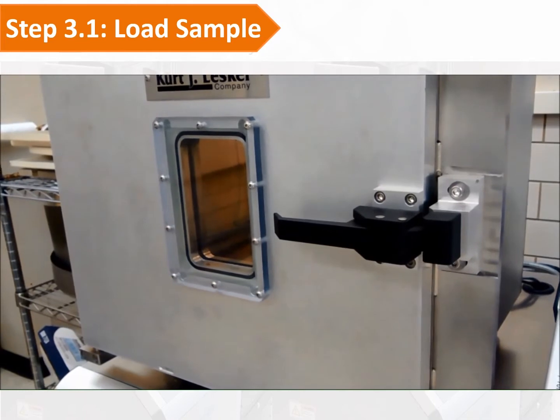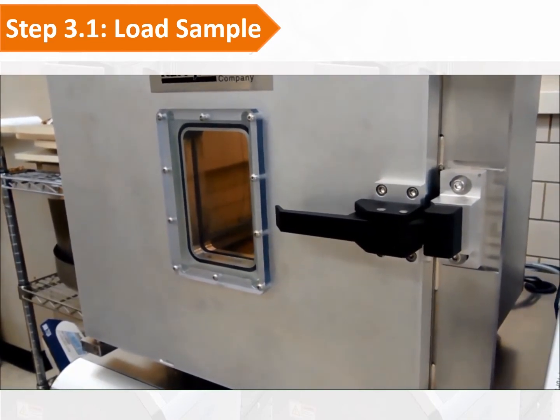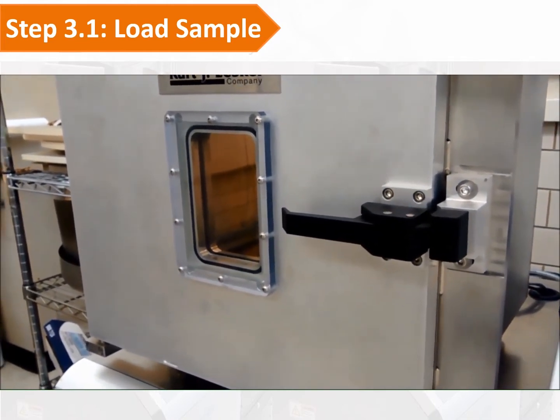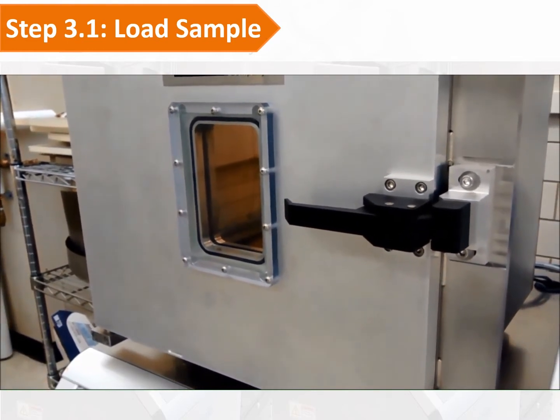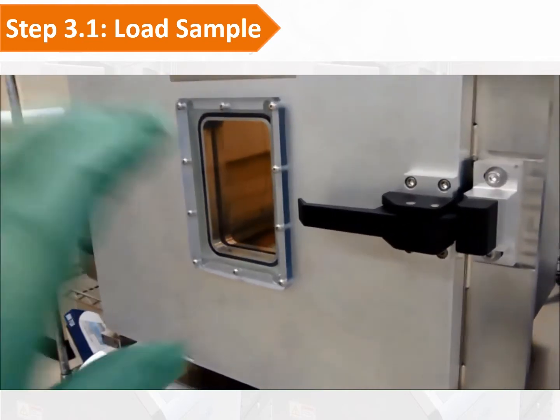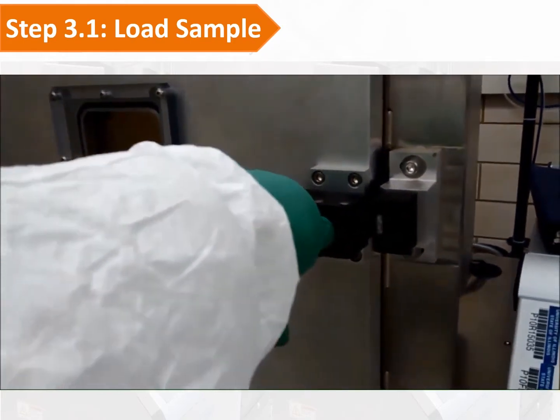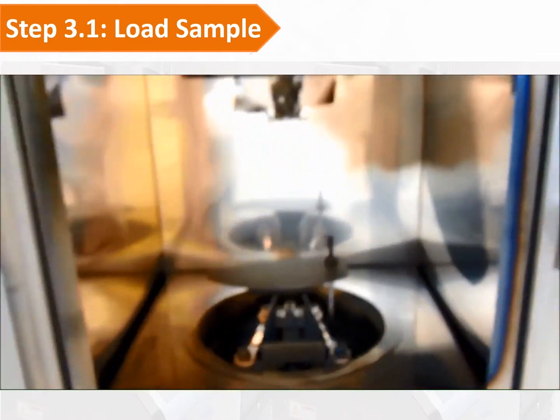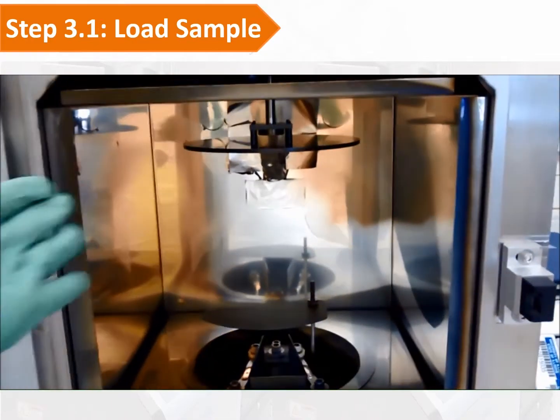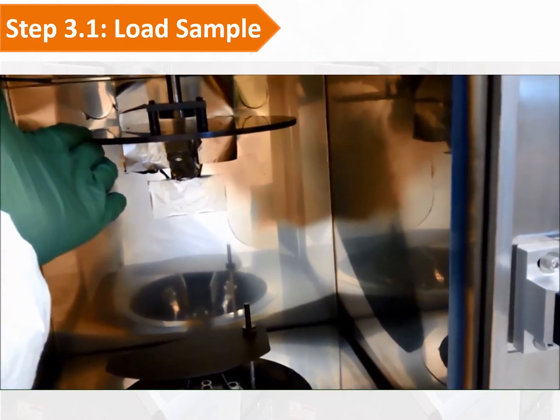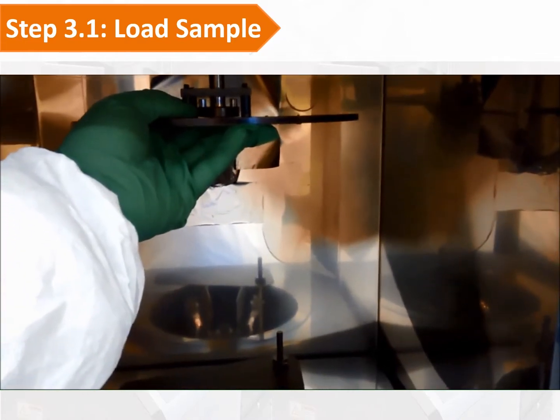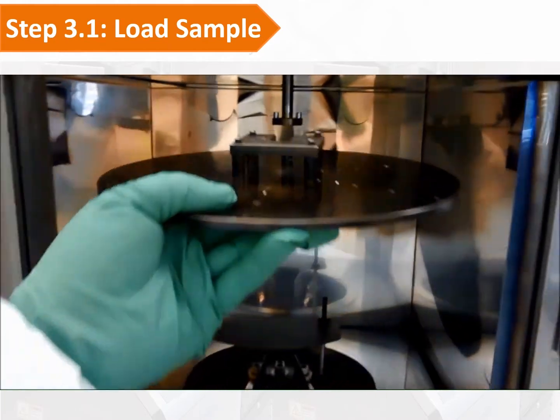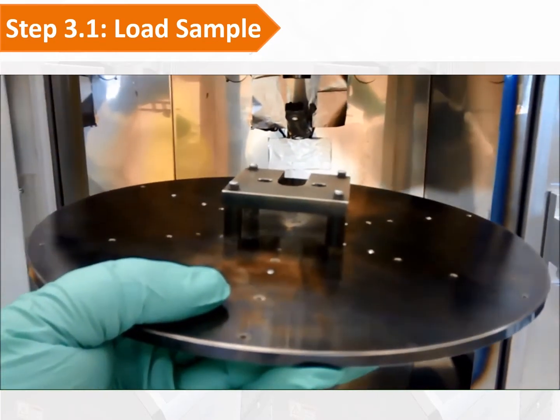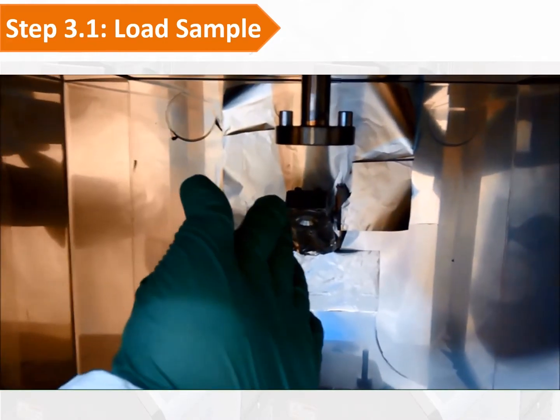Step 3, load sample and deposition materials. This is the first part, 3.1. We will talk about how to load the sample into this deposition chamber. So we need to open the chamber door first, and then we can remove the sample holder from the chamber. We just remove the plate, lifting it slightly, and slide it out over the alignment pins. During this process, please be careful with the crystal monitor and do not touch it.